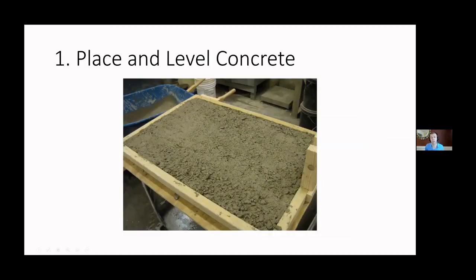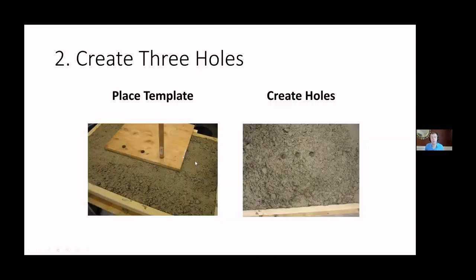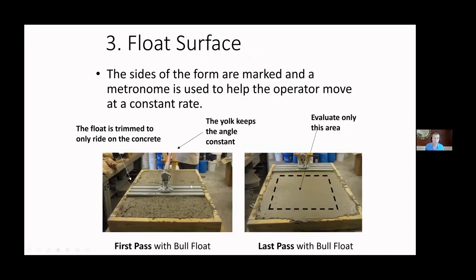Let's show you what I'm talking about. So there is the concrete struck off, right? Then we come in with this template. We form 3 1-inch diameter holes. And then we come in with this float. This float has been trimmed, so it only rides on the concrete, not on the wood. It actually has a yoke over here. It holds it at a fixed angle. It goes back and forth. We actually moved at a fixed speed, and we say, how many passes does it take to do 2 things? To close the holes and to make it smooth.